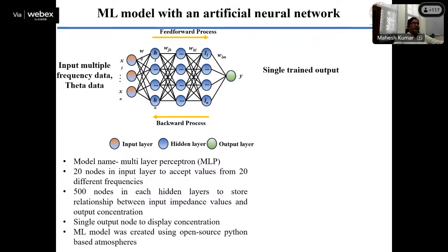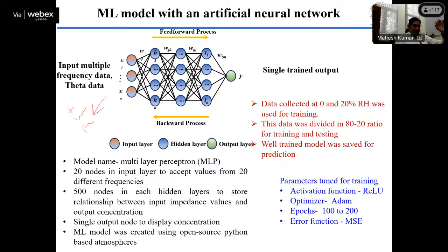Here we are using an artificial neural network. We put in all these parameters, frequency, humidity, phase, as input, and our output is the prediction of the exact H2S value. We collected data at 0 and 20% humidity for the training, and this data was divided 80 and 20 for training and testing. So 80% of the data we used for training and 20% for testing. The well-trained model was then used for the prediction.